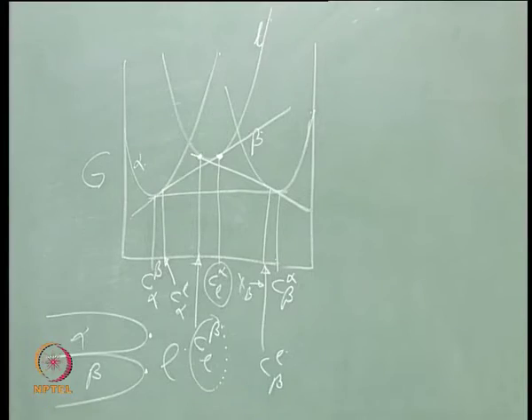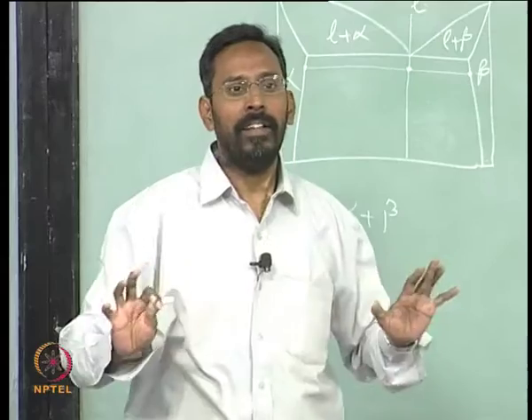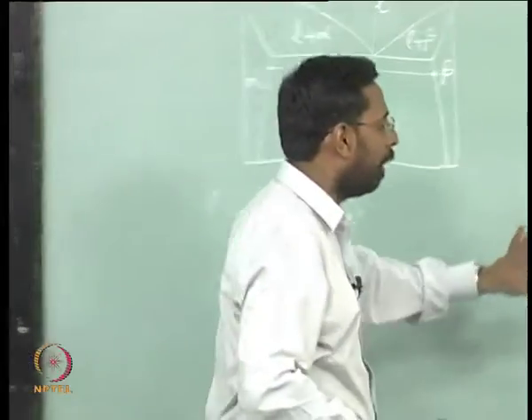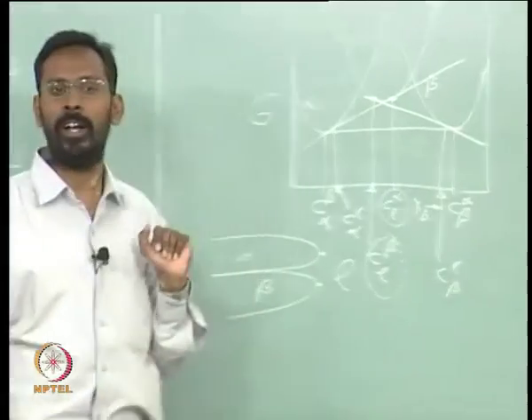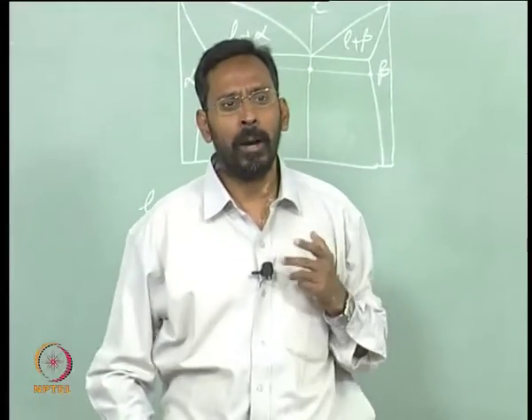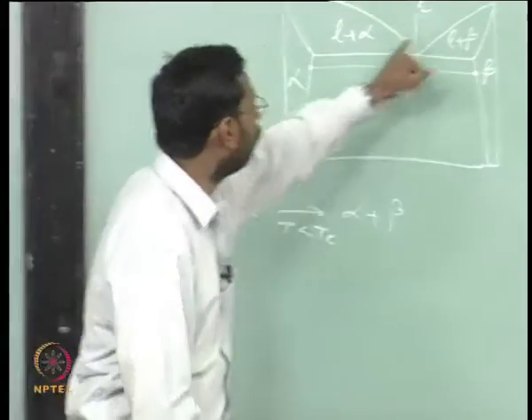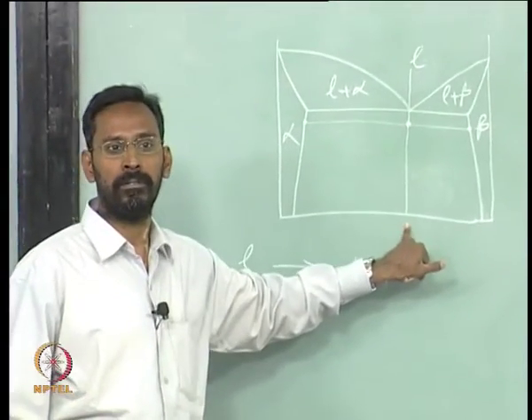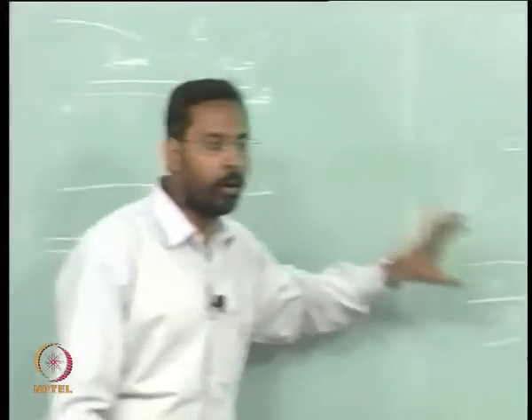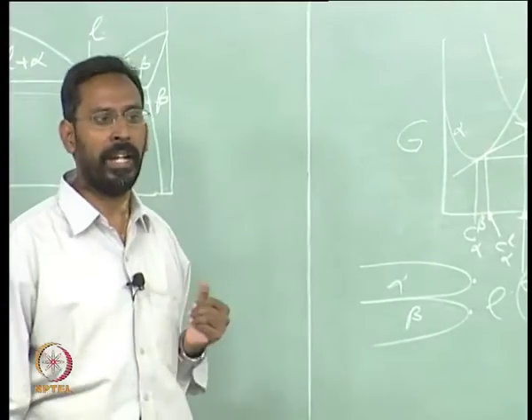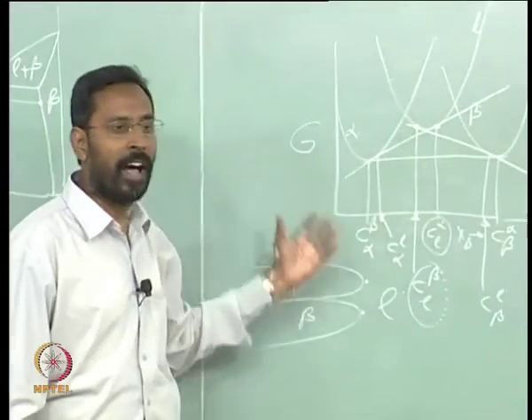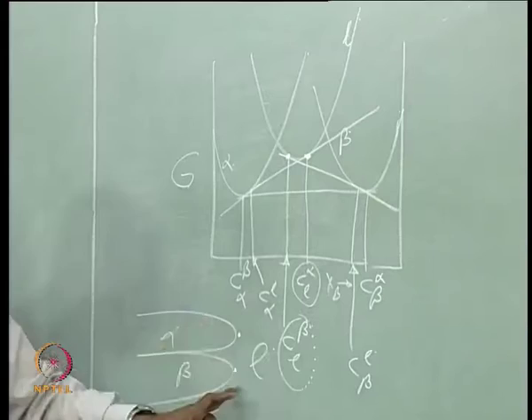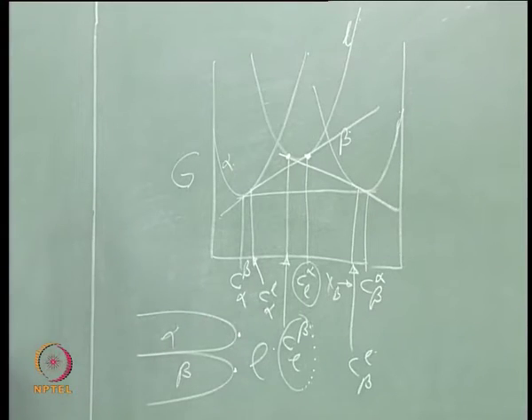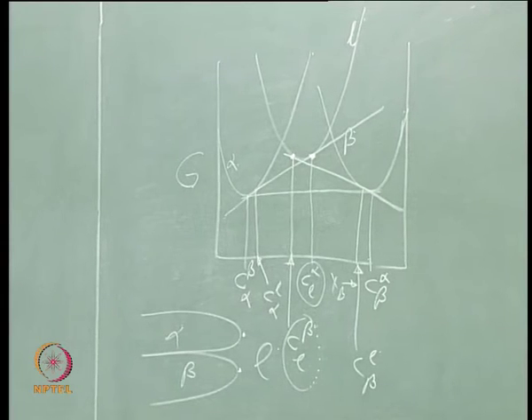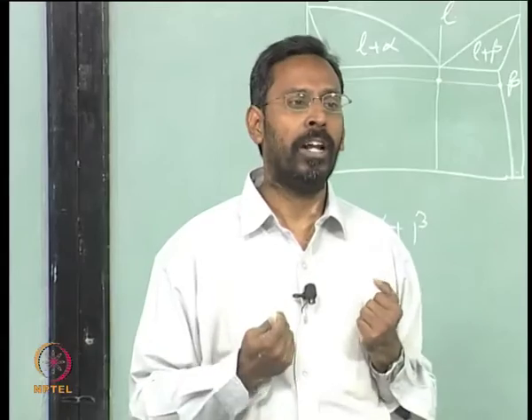This means that liquid is not having the same composition everywhere. If I go far away from this alpha plus beta interface, what is the composition of the liquid? It is same as that of the eutectic composition. This is only because of the local equilibrium that has to be maintained, and if this composition is not maintained, then alpha and beta cannot exist in equilibrium with liquid. They will possibly dissolve back into the liquid.